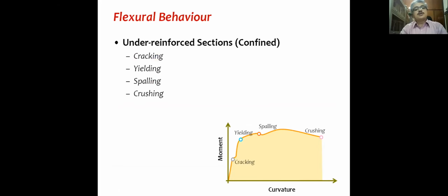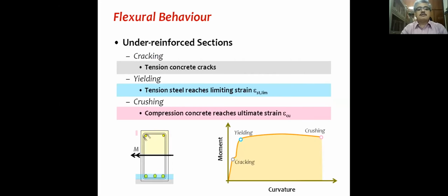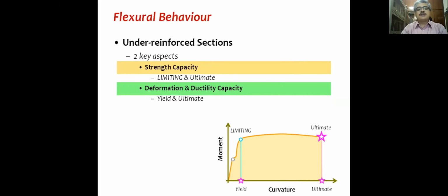So essentially, if you look at the moment-curvature response of a reinforced concrete section, these are the salient features: cracking, yielding, spalling, crushing, and probably buckling of compression reinforcement thereafter. But for our interest, the important aspects are cracking, yielding, and crushing. And if we idealize this response, we see that there are two aspects we need to look at: two levels of strength.